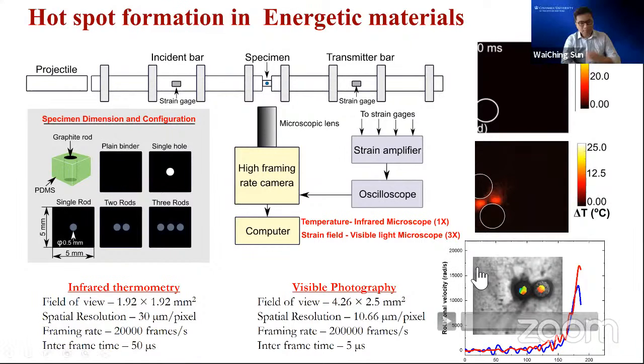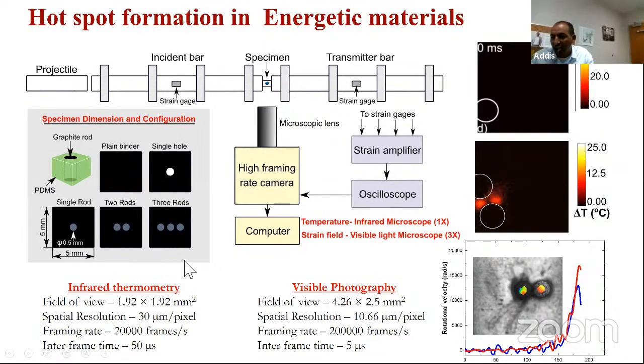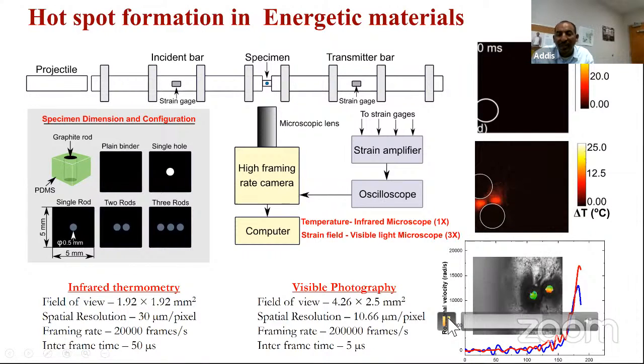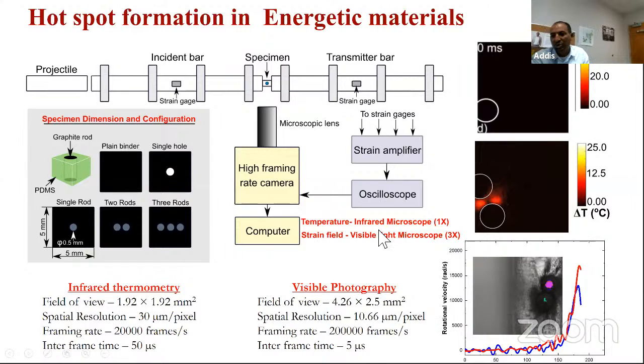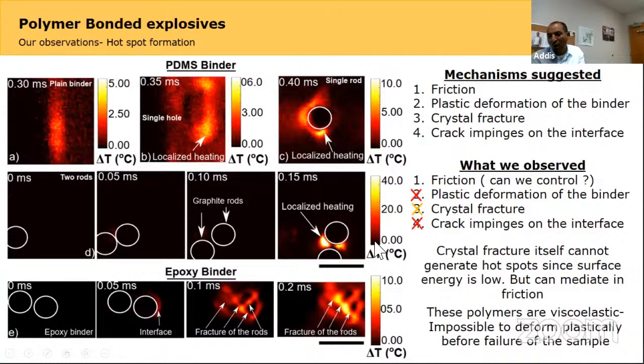So what actually happens is that the rod which has 2 crystals has the largest temperatures, and we found that the temperature rise is actually not because of the deformation, but because of friction. And I told you earlier that we measure the rotation of the crystals that happens in this material. That is actually the main cause of the increase. This rotation increases suddenly at these positions. So this is just explaining what happened on these 2 rods, but I will stop here.